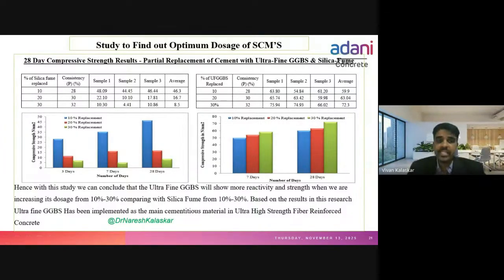When we added 30% silica fume, the compressive strength at 28 days drastically went down to 8.5 MPa. So when you increase the silica fume content from 10 to 20 to 30%, the strength is coming down. But when you replace 10% of cement with ultrafine GGBS, you get 59.9 MPa strength. When you increase 10% more, you get 63.4 MPa. When you replace 30% of cement with ultrafine GGBS, you get 72.3 MPa compressive strength.